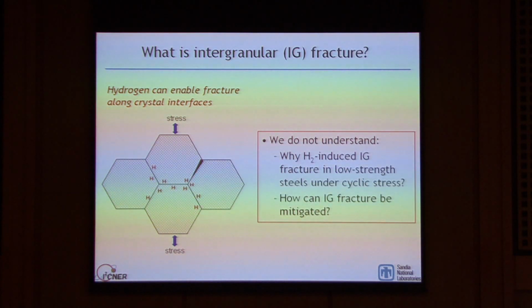But we really don't understand a lot about this process, particularly under the action of cyclic deformation. So I think two of the questions we can try to address in this thematic area are: why does hydrogen-induced intergranular fracture in these low-strength, low-cost steels happen, and why does it propagate along grain boundaries, especially under cyclic stress or cyclic deformation? A related question is, can we try to mitigate this intergranular fracture to improve the fatigue crack growth resistance of these low-cost steels in high-pressure hydrogen gas?